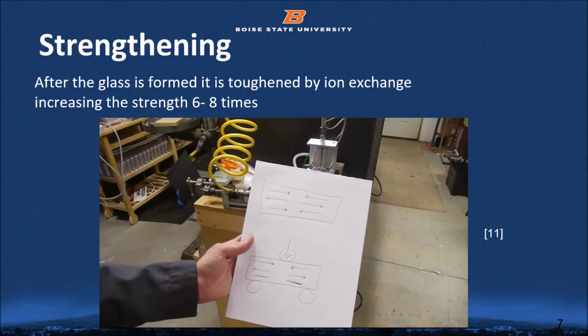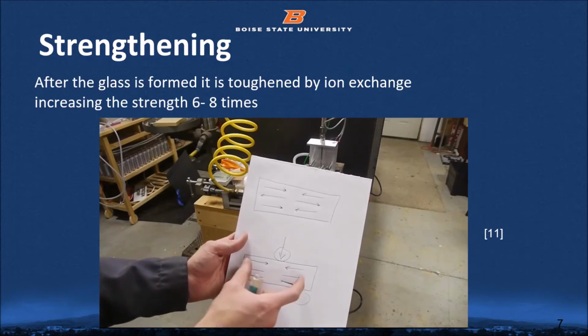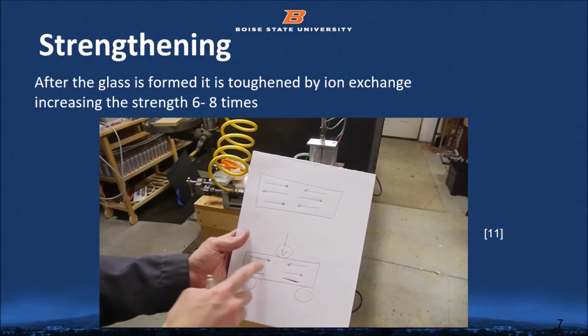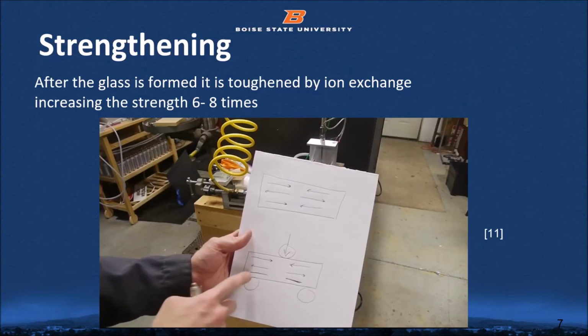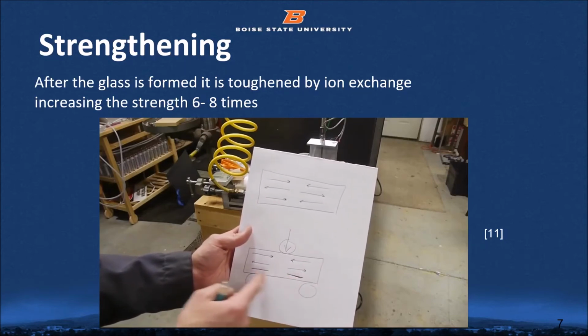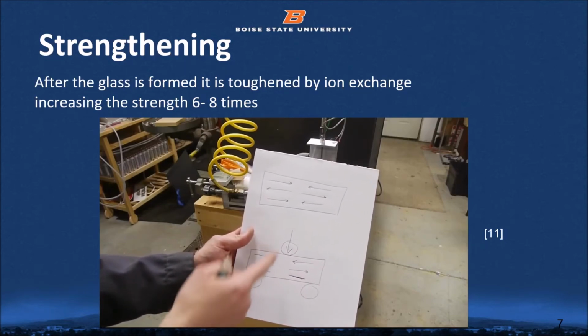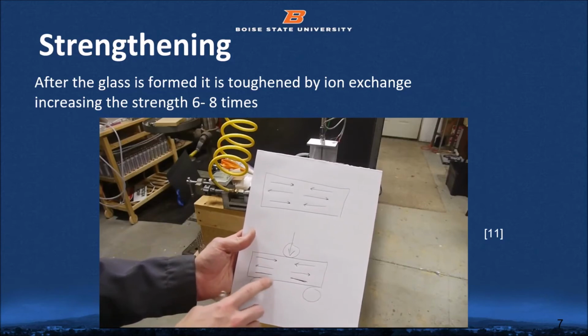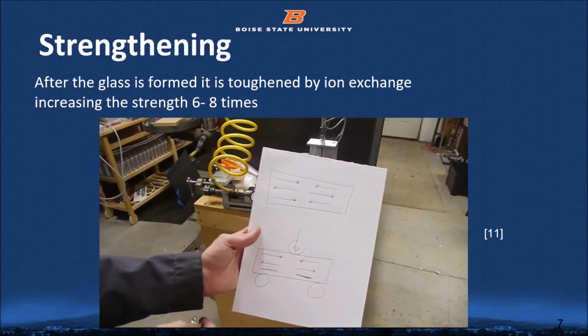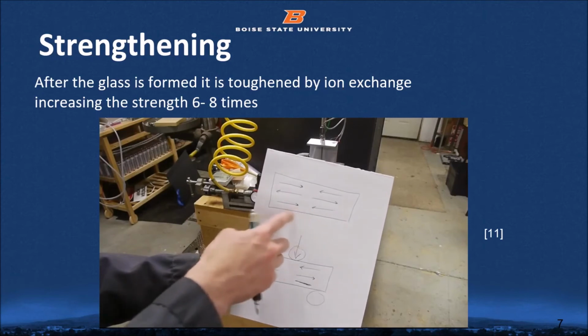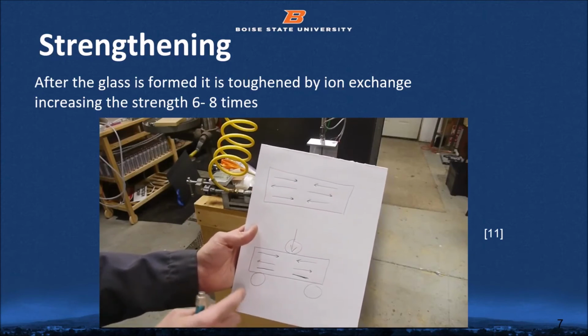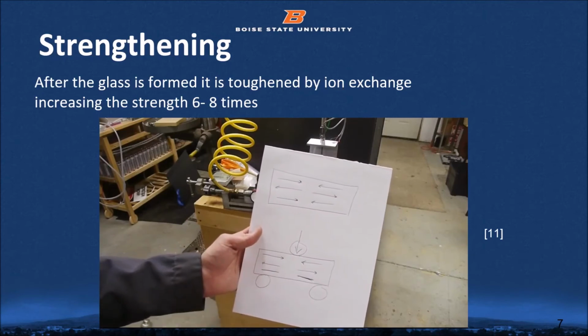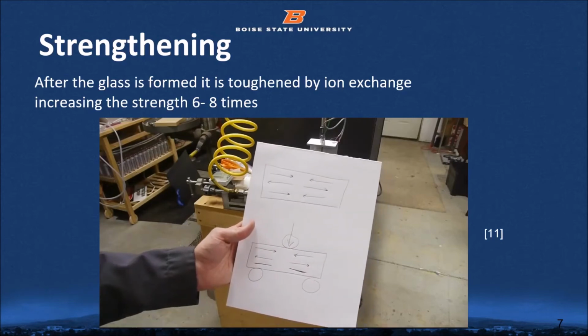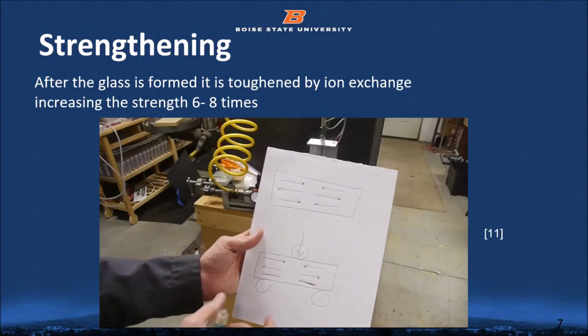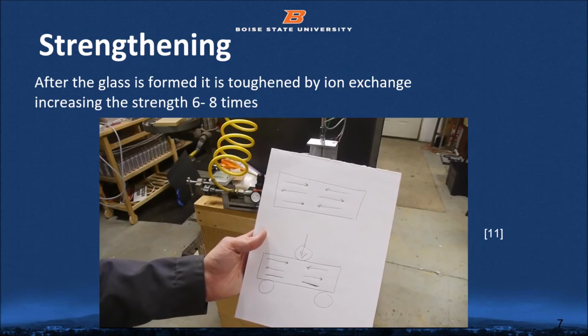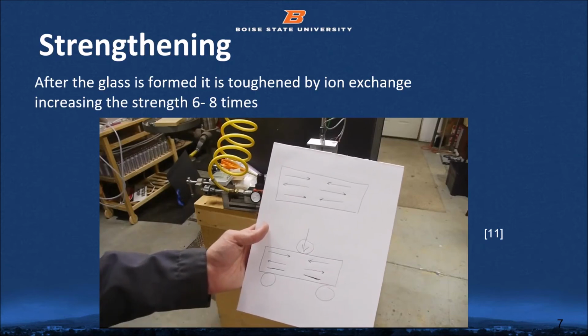So later, when we load the piece in bending, the top gets to be even higher in compression. The center is still in tension, but the bottom layer, which would normally be in tension in a bending situation like this, is now either neutral, or at least it's offset quite a bit, because that residual compression is sort of canceling out the tension that would be created by this loading scenario. So we've effectively strengthened the piece of glass by preloading it in compression. We're able to get rid of some of that tension loading.